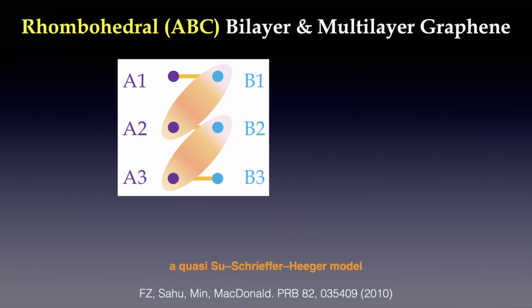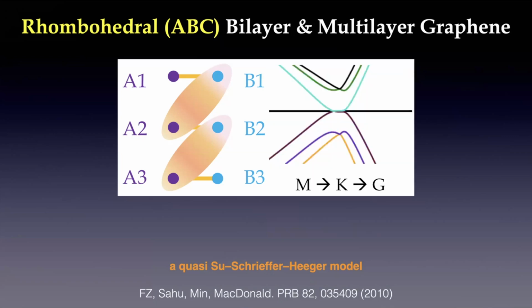Because of the dimerization, this system reduces to a two-band model, right? You always have a low energy site A1 and Bn, this kind of bilayer system. One low energy sublattice on the top layer, one low energy sublattice on the bottom layer. And the hopping between them is an n-step process, depending on the number n. In this three-layer system, hopping from A1 to B3: the first step is from A1 to the first dimer, then to the second dimer, and then to B3, three steps. So that's why in trilayer the dispersion is p to the third, p to the third.